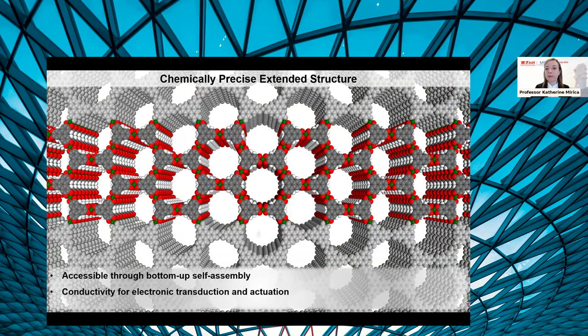The chemical precision is really valuable for understanding structure property relationships, but also the fact that this material can be assembled from the bottom up through the process of self-assembly and coordination chemistry gives us bottom-up control over those structure property relationships. And the intrinsic conductivity that is embedded in this material by design through high conjugation of the ligands and the metals that are used to construct the framework, as well as through space orbital overlap of these stacked layers, is really beneficial for electronic transduction and actuation of chemical information. So when something binds to the surface, that binding event can be transduced as a change in electronic properties of the material.